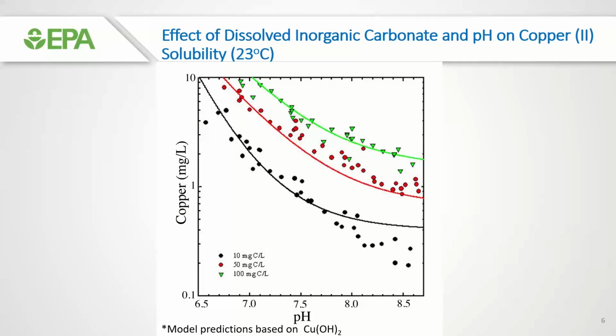Copper levels are actually, as it turns out, pretty easy to predict, and that's the nice thing about copper relative to lead, in that newer copper is going to give you the highest copper levels. It's pretty predictable, and you can actually do precipitation experiments to see what copper levels might be in a particular water. But we're using precipitation experiments here to simply precipitate copper in the presence of different pHs and different dissolved inorganic carbon concentrations. The thing to take from this is that copper levels are very sensitive, and the experimental data is in dots, and the model data is in the solid lines. But the point is that the dots, the experimental data, match up with the models really nicely.